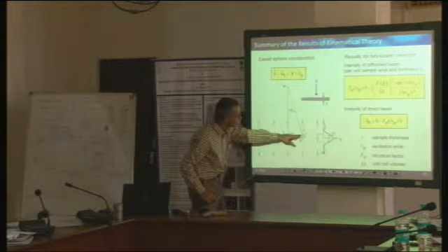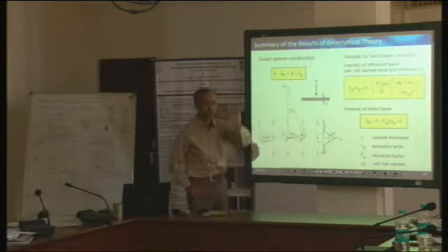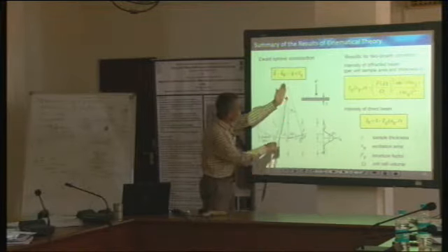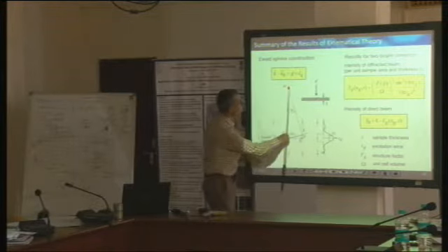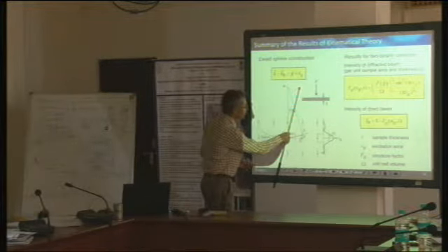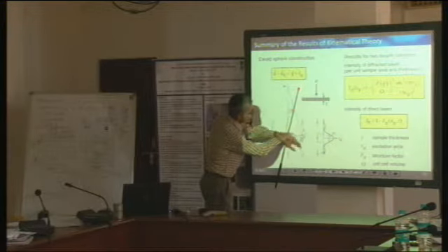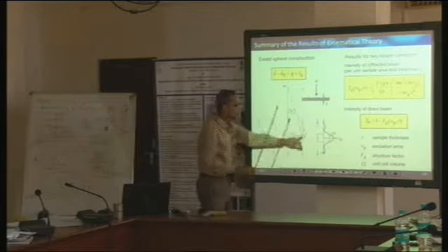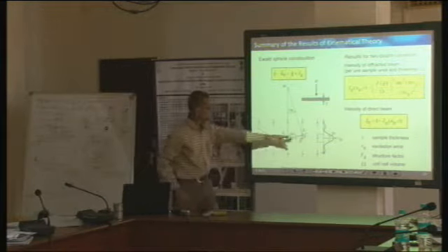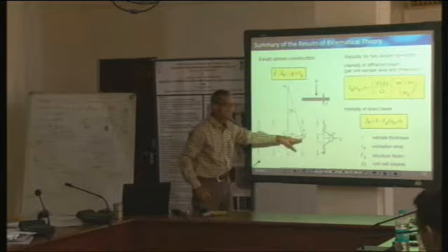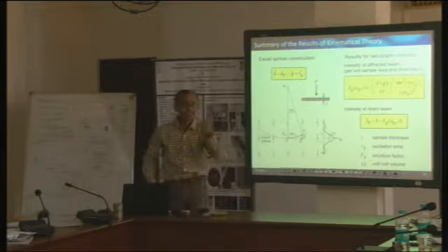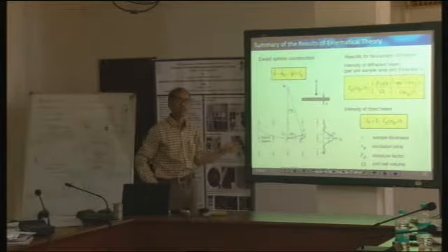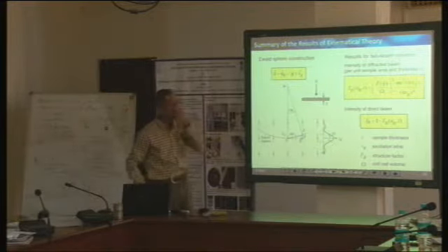Let's say this magnitude of S is maybe 2, just for the sake of some idea, some number. Now I tilt it in such a way that, instead of having it like this, I make it something like this. Then the Ewald sphere will come closer to this reciprocal lattice point, and let us assume that it hits it exactly. Now S is equal to 0. So in the latter case, it exactly satisfies the Bragg diffraction condition. And of course when it exactly satisfies the Bragg diffraction condition, there is going to be more intensity.